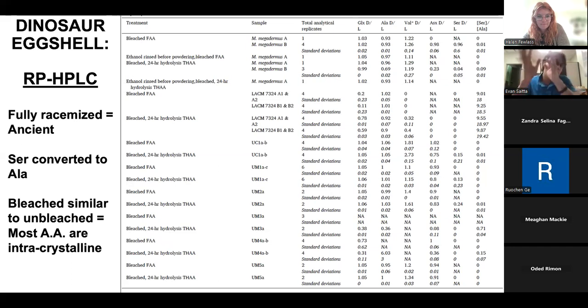Now, again, we can look at the racemization patterns in these amino acids, and unlike the dinosaur bone, these eggshells are consistently fully racemized, suggesting that they are very, very ancient. Not only that, but we see conversion. We interpret conversion of serine to alanine, which is also a diagenetic process within these amino acids in these eggshells. And then finally, the samples of eggshells that were bleached, we were talking about that oxidative bleaching method that removes contamination. When we compared the bleached eggshells to those that were not bleached, you get very similar results. And this would be consistent with the idea that most of the amino acids we are detecting are indeed the intracrystalline amino acids. So whatever is left behind is the stuff that is presumably locked away within this closed system within the calcite crystal.